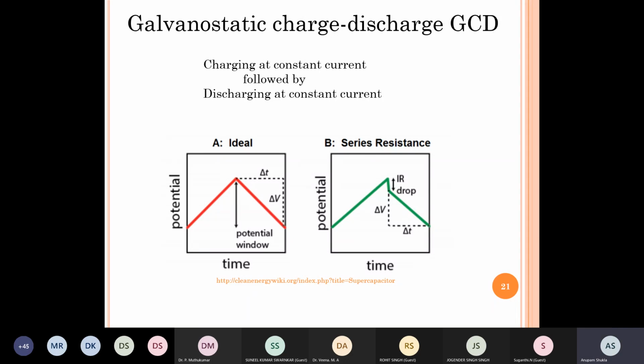Okay. The final part of the first part of the talk is on galvanostatic. So how to characterize a capacitor. There are two different techniques which are used, the GCD, the galvanostatic charge discharge, which is charging at constant current followed by discharging at constant current. This is how an ideal capacitor will behave because it shows the linear behavior. During charge, the potential will rise. And when the discharge is done, the potential will go down.